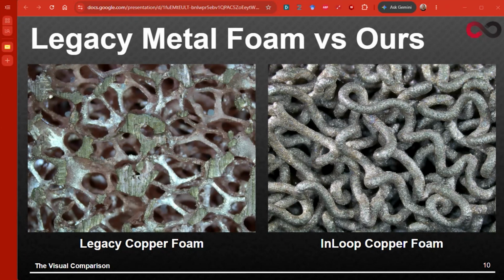So we're printing on the order of 210 Celsius in order to embed the actual structure. And then we go through additional debinding and sintering steps in order to remove the polymer and then fuse the metal.